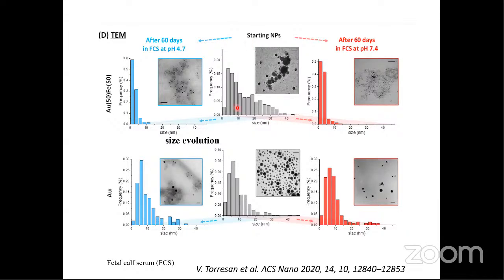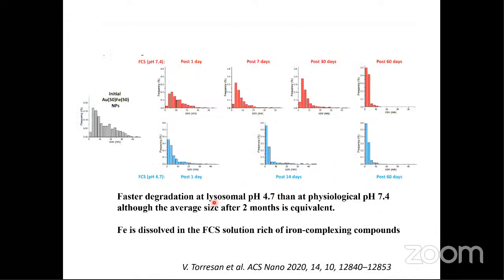You see here, for instance, the starting nanoparticle, and 60 days after at pH 4.7, the size has drastically reduced. The same happens here. There is a huge size evolution, and the faster degradation occurs at lysosomal pH 4.7 than at physiological pH. We can see here, following in time, the evolution with TEM, and although it's faster at 4.7, when we reach 2 months, the sizes are almost the same, so iron gets dissolved in the buffer.